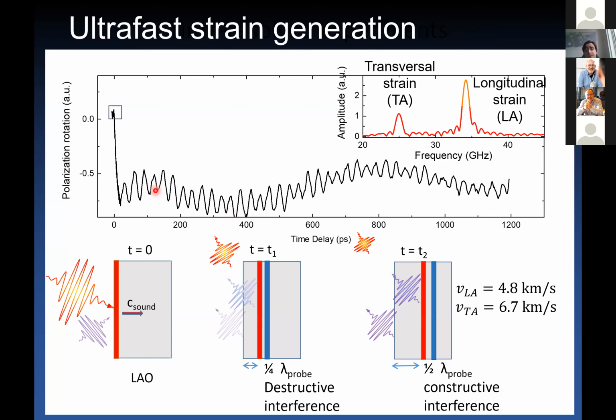In addition to this Raman mode activation, when we excite the crystal lattice of lanthanum aluminate, we also observe the generation of ultrafast strain. So we observe this again by measuring reflectivity and polarization rotations of a light probe. And if you do so, you see a pattern of oscillations occurring in the gigahertz range. So this pattern of oscillations corresponds to the propagation of a sound wave across your crystal. And the oscillations are a pattern of destructive and constructive interference of the probe pulse that is either reflected from the pristine surface of your material or by the propagating strain wave.